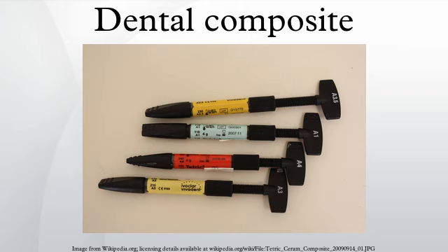Although corrosion is no longer a major problem with amalgam fillings, resin composites do not corrode at all. Disadvantages: composite shrinkage and secondary caries. In the past, composite resins suffered significant shrinkage during curing, which led to an inferior bonding interface. Shrinkage permits microleakage, which, if not caught early, can cause secondary caries, the most significant dental disadvantage of composite restoration.